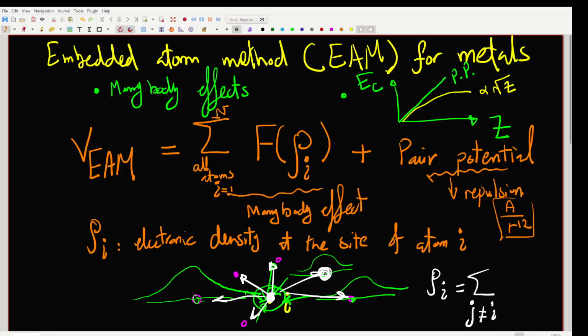That's to say, it's a sum over all the surrounding atoms. You calculate the distance between the two atoms in a vectorial fashion, Ri minus Rj, right? And then you plug in this distance in some expression for the charge density to know how much charge density exists at the location I. And typically, so this is rho due to atom J. Typically, this Gaussian shaped charge density is an atomic charge density calculated previously using quantum mechanics.